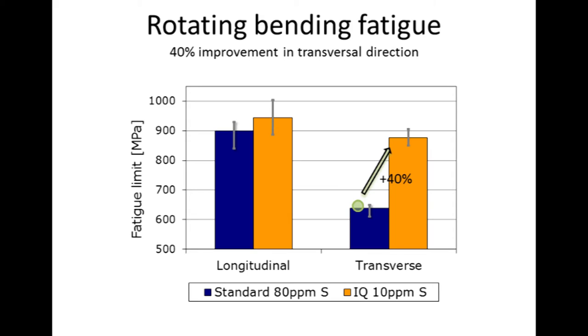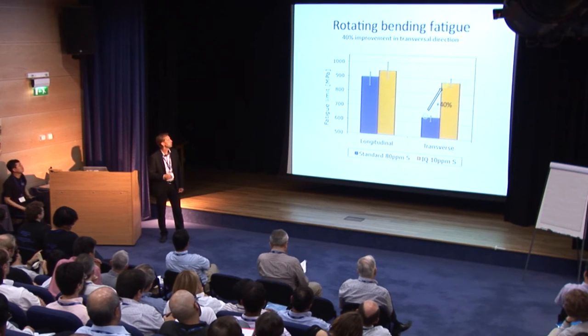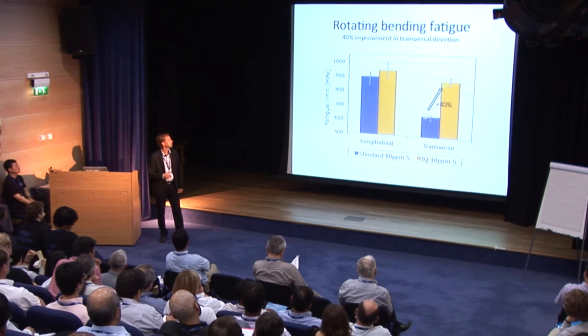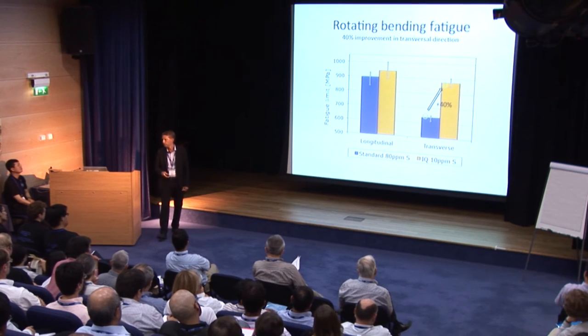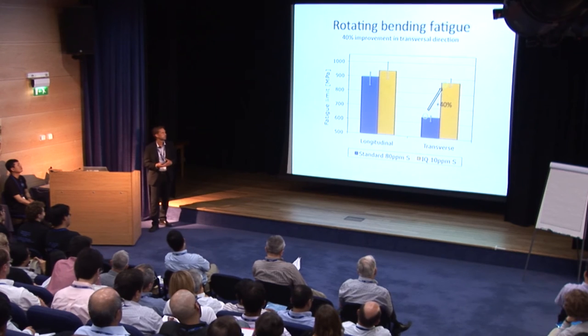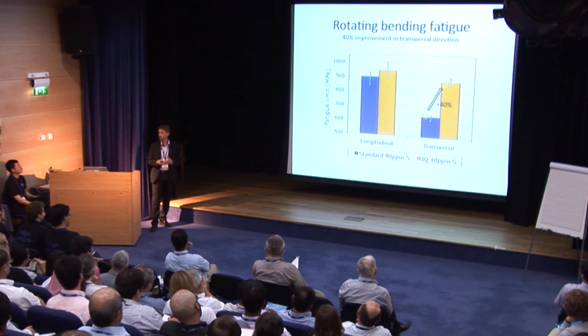For instance, if you look at fatigue, in this case just rotating bending fatigue, we see that longitudinally, there is not a big difference between different steels nor the cleanliness levels. But if you go into the transverse direction and start to have this complexity, then you could really benefit. So isotropy should be considered when it's needed.